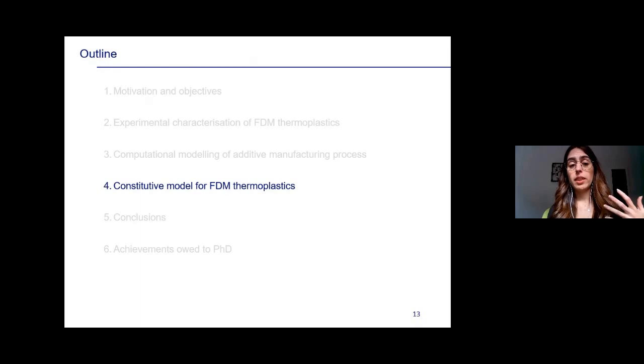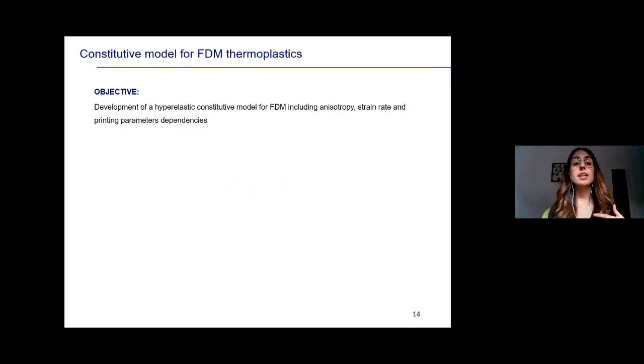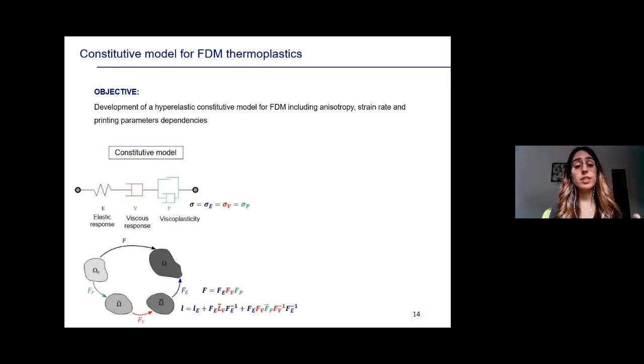Now, I would like to continue with the third and last part of my research. The objective of this last part was to develop a hyperelastic constitutive model for fused deposition modeling components. In this model, we include the anisotropy due to the 3D printing, the strain rate dependency, and also other dependencies due to the printing parameters. So the first thing that we did is we developed the formulation of this model, in which we take into account that these materials present an elastic response, also a viscous response, and in the case of longitudinal specimens, we observe a viscous plastic response.